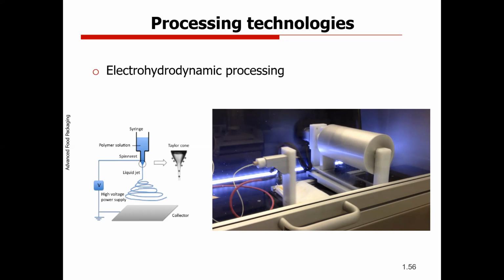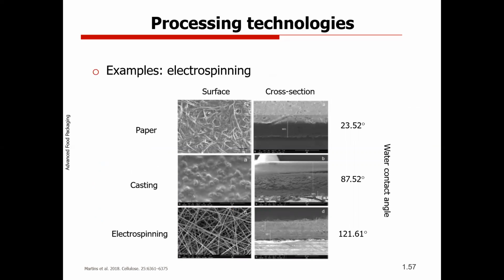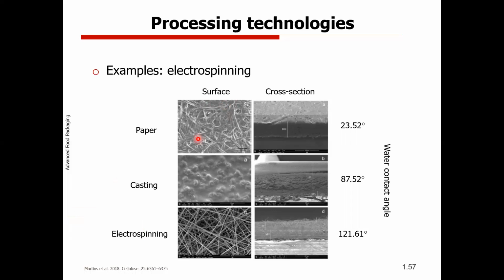We did that on a different surface. In this case, I'm showing paper, so we tried it on paper, and we compared the paper with nanofibers, compared with the casting, and only the paper. So in this image, you can see the paper. This is the cross section. Here you have the paper with a layer of ethyl cellulose, which was the polymer that we used to make this coating. This is by casting, and then you have ethyl cellulose by fibers.